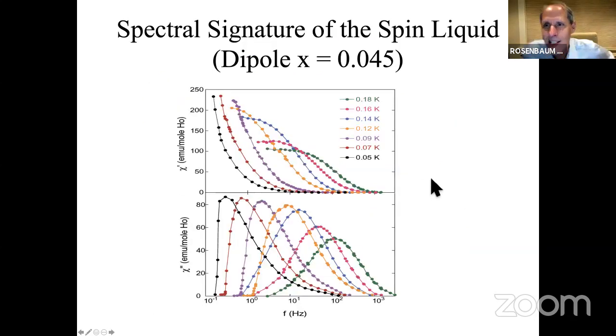So what does the spin liquid look like? I showed you the spectral response before of the spin glass. And in a lot of ways, this is the anti-spin glass. So what you're looking at here, and I'll explain what I mean by that, is the real part of the susceptibility at a series of temperatures, 0.18 Kelvin down to 50 millikelvin, 180 millikelvin to 50 millikelvin.